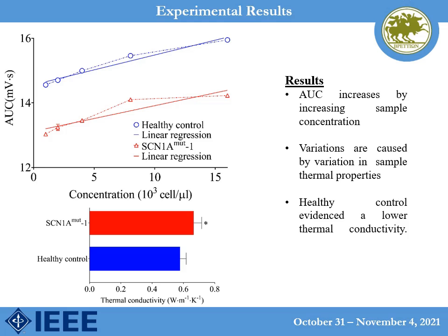However, here in the slide, differences between the samples are evidenced. To this end, the thermal conductivity can be related to the area under the curve by considering the physical and electrical characteristics of the sensor and by considering the Maxwell model, which describes the thermal conductivity of a solution in which spheroids are dispersed.